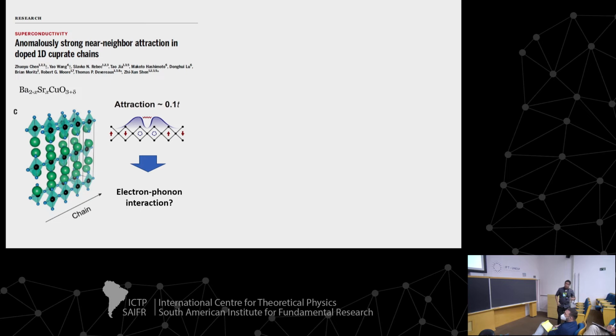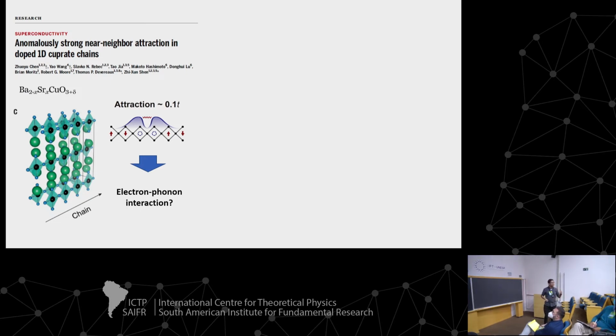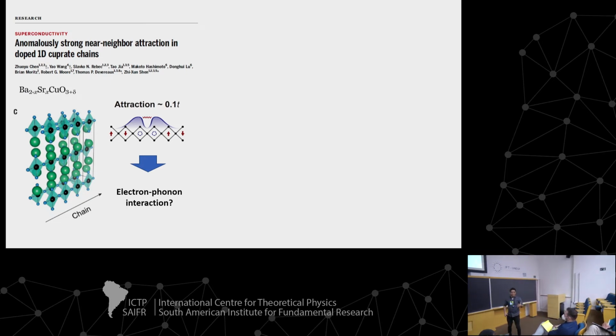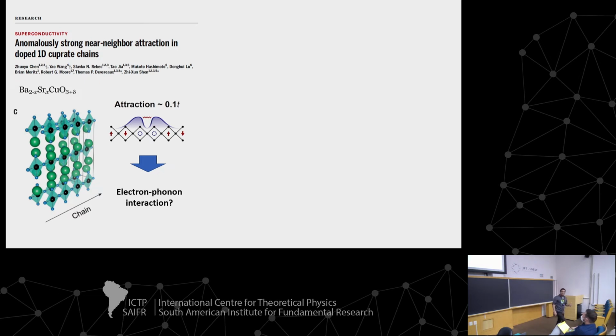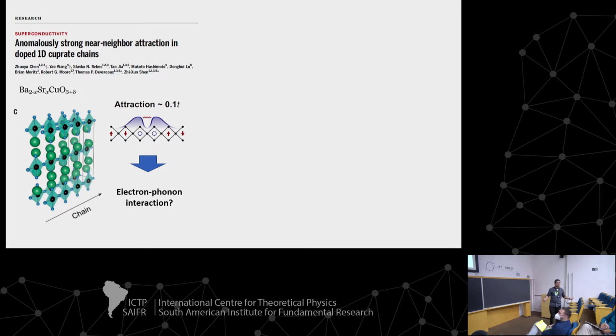Okay, finally, still discussing cuprates. A very recent result for some kind of cuprates that have weakly coupled chains. They analyzed this by ARPES. They see that they can only explain the energies that they measure if they include in their model an attractive interaction, a nearest neighbor attractive interaction between electrons. So in other words, just the Hubbard model is not enough to explain superconductivity in cuprates. You have to put in long-range interactions.